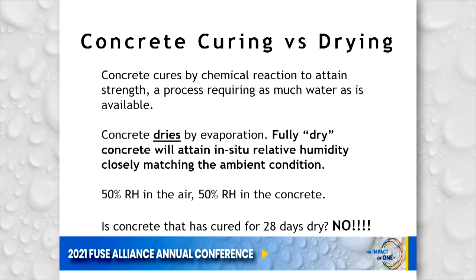Concrete dries by evaporation, and it's important for you to know that fully dry concrete will attain in situ relative humidity closely matching the ambient condition. If there's a 50% relative humidity in the air, the concrete can attain 50% relative humidity. It can never be drier than that. But if it's wetter than that, there needs to be a question as to why.